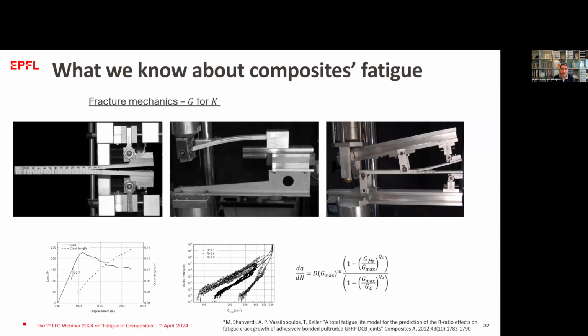This is again from work that we did here at CC Lab 10 years ago. And we produce FCG curves. We produce R curves for static loading. We produce FCG curves, and also we develop models to fit this behavior. Here again, there is a discussion about what kind of parameters it should be. It can be G, it can be delta G, it can be square root of G, or another parameter that defines the load that we apply to the material. And on the other side, we have the speed of the crack propagation.